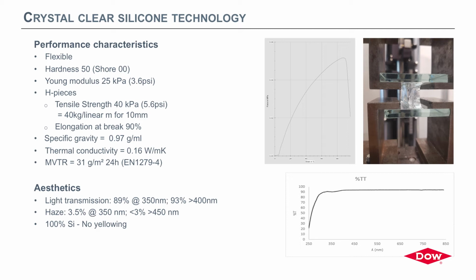In terms of aesthetics, we're talking about crystal clear. Here you can see the light transmission measured according to the ASTM D1003. You see that we are around 90%, depending on the wavelength that you take into account. And the haze is also excellent, less than around 3%. This is still 100% silicone technology, so it comes with all the durability and also the non-yellowing aspects that you can anticipate for this system.